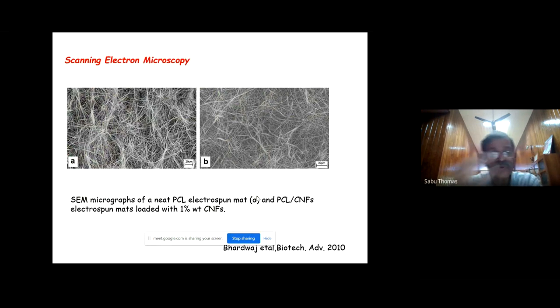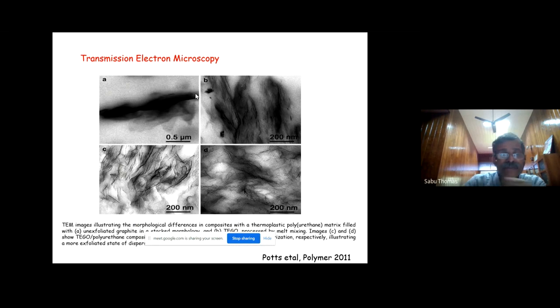Polycaprolactone. We work a lot on PCL. Look at this, this is PCL. This is PCL with 1% of carbon nanofibers. We could get finer fibers when you use 1% of carbon nanofiber. Let me show you another important